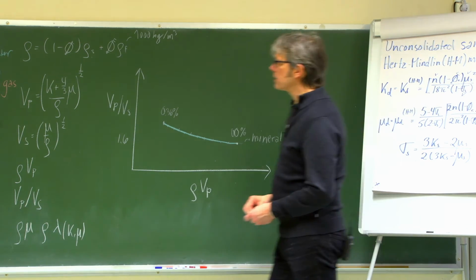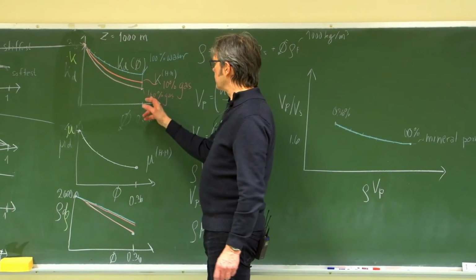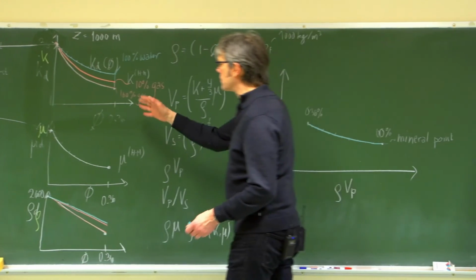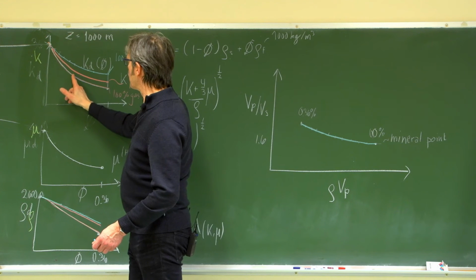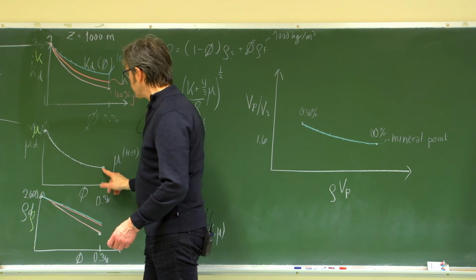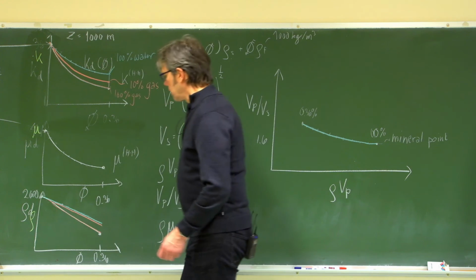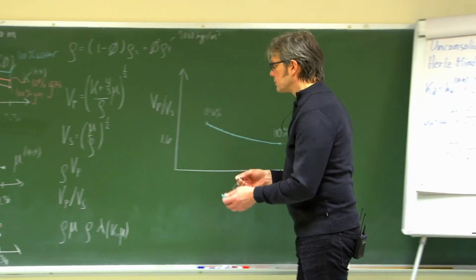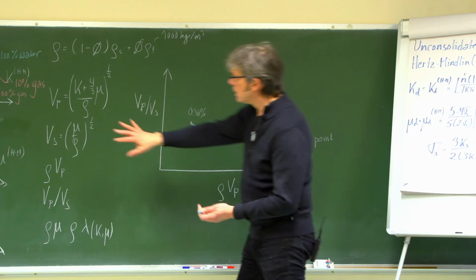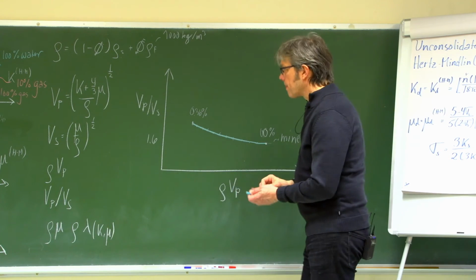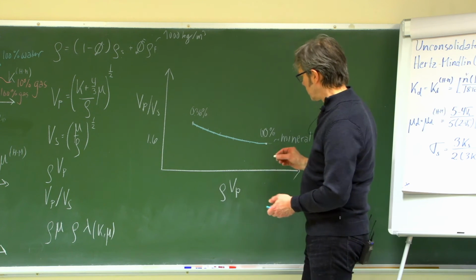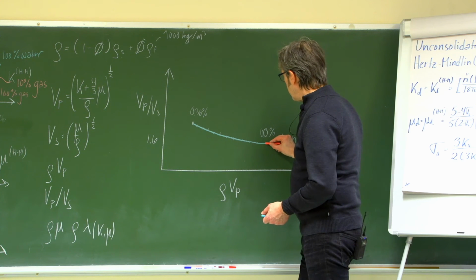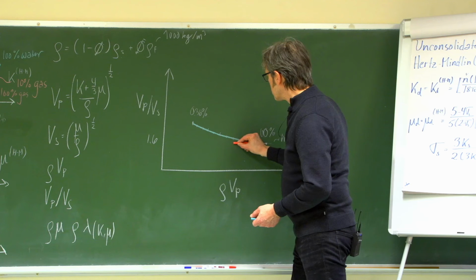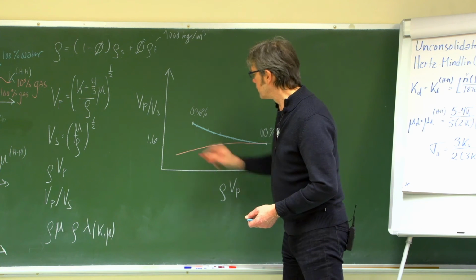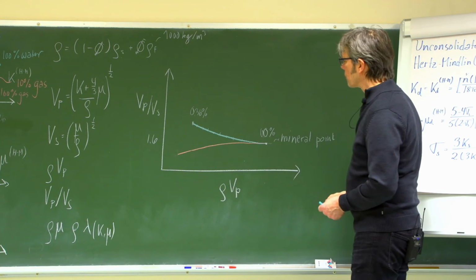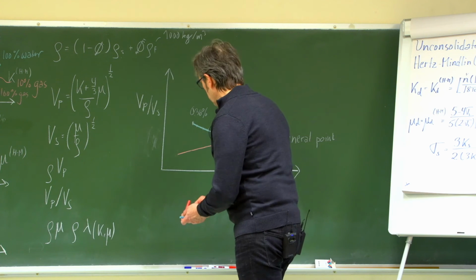So what happens if I then use the 100% gas and do exactly the same, just sampling the points along the lower red line here and combine it with the similar points as before along that one, and then use the lower red line here. If I just combine these three curves, as input to these two simple formulas, it gives me a red line here. It's going down here, something like that. So the 1.6 should be maybe a bit lower down here.